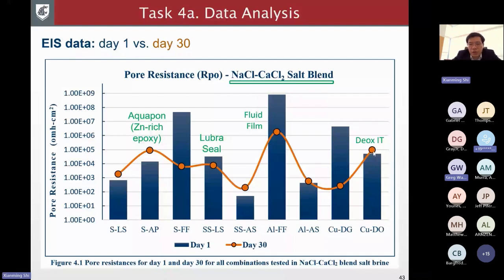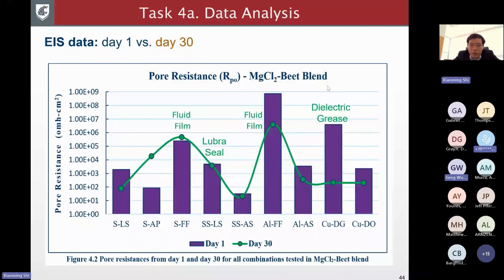If we look at the magnesium chloride beet juice blend, it's somewhat similar. You see some clear winners like Fluid Film. Here again, Fluid Film for both aluminum and carbon steel substrates, and then Lubra Seal for stainless steel substrate, and then dielectric grease for copper substrate.